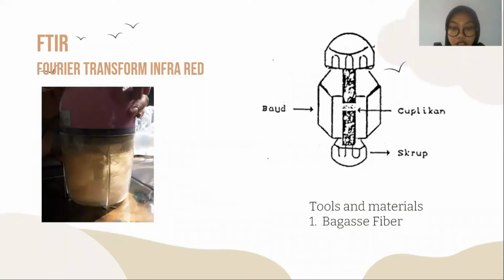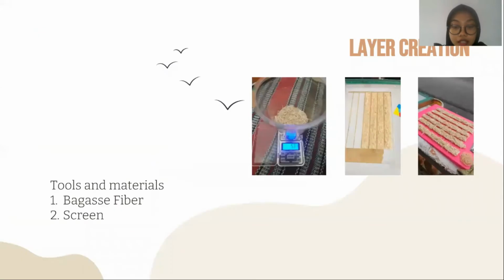And then validate the decrease in lignin level with the FTIR test. The FTIR testing tests specimens in compacted powder form. The tested powders were fiber powder before the delignification, the fiber powder after delignification without natrium hydroxide, and fiber powder after the delignification with 3% natrium hydroxide. FTIR test is a test that uses infrared light to identify the compound. The analysis is carried out by looking at the resulting spectrum, where the specific peak indicates the type of functional group of the compound. And then layer creation.